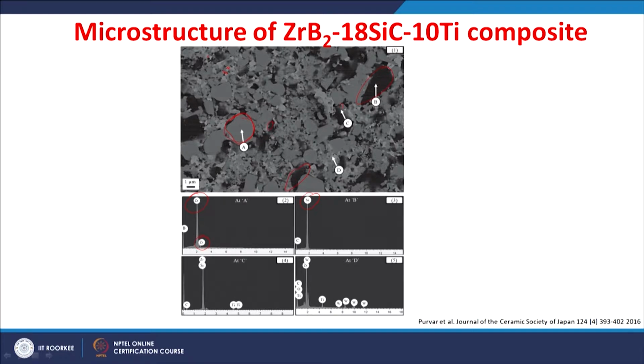And we can see the zirconium and silicon both are present along with the titanium in the matrix, and we can also see certain contamination from the ball milling medium. Ball milling was done mainly to mix these powders of zirconium diboride, silicon carbide and titanium. But the ball milling was done by using balls of tungsten carbide. So, tungsten carbide came into the powder mixture. It still remains, so you have a contamination even after the sintering.